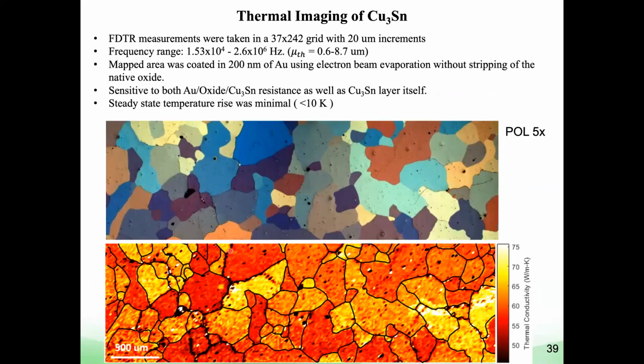So here's the thermal conductivity map. You might not be able to see my mouse because it's red on red here, but you can see that neighboring grains can have quite different thermal conductivities. That's this red and yellow here. Red's low conductivity and yellow is higher conductivity. You can see the crystal orientation is different from this polarized light microscopy image, but you can't use the color of the polarized light to tell you the crystal orientation. But you can tell that it's different.